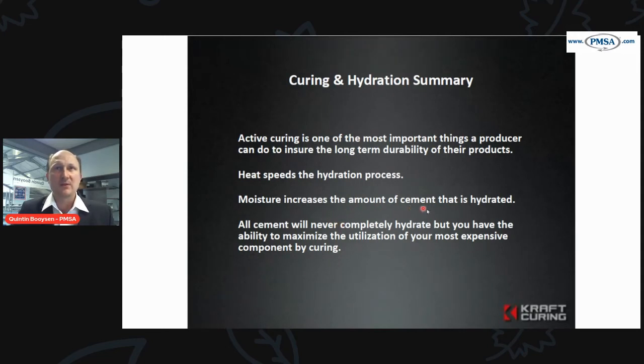Moisture increases the amount of cement that is hydrated, so the more moisture after you've made the mix. In the curing process, not up front, we don't want to put too much water. As we all know, too much water in the beginning when making concrete is not good for the strength, but high water content after that, let's say the 8 to 24 hours, is critical because that allows the cement to hydrate. All cement will never completely hydrate, but you have the ability to maximize the utilization of your most expensive component, which is cement, through a good curing system.